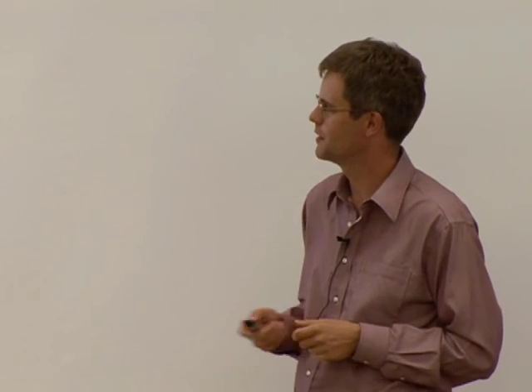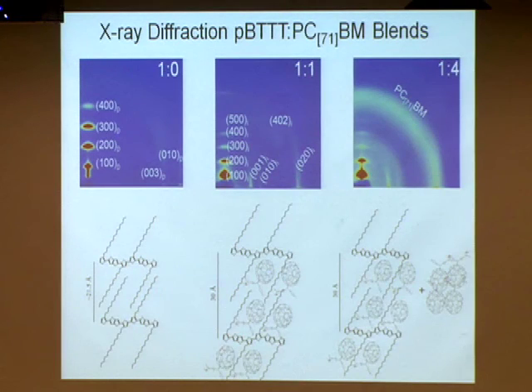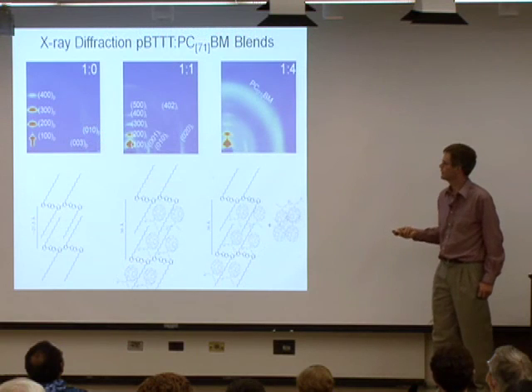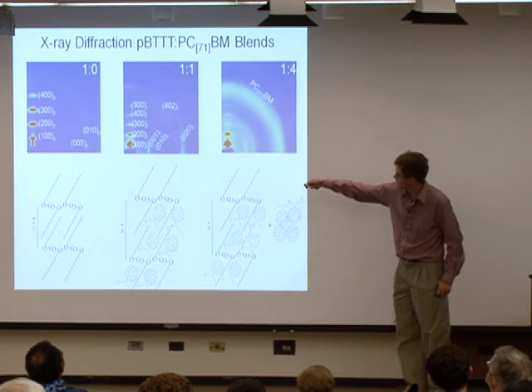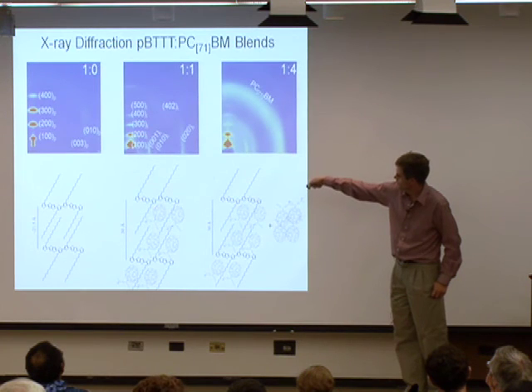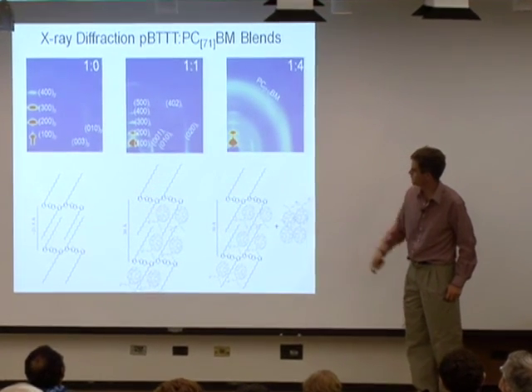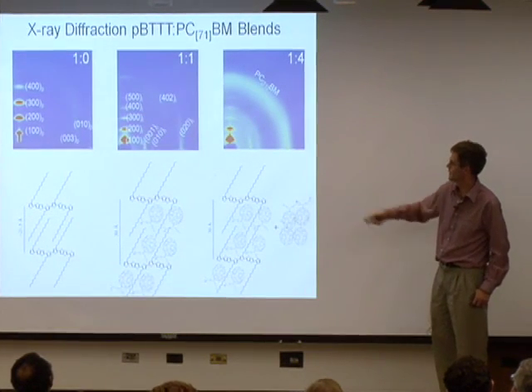So recently we saw some strange behavior with one of these polymers, and we found that when we had half polymer and half fullerene, the solar cells hardly worked at all, and with other polymers, that was actually the best ratio. So we collaborated with Mike Toney up at the synchrotron and used X-ray diffraction to learn how the molecules were packing. And to make a long story short, what we learned is that for some polymers, there's enough space between the side chains for the fullerene to insert itself in between there. And then for other molecules, there's not enough space.